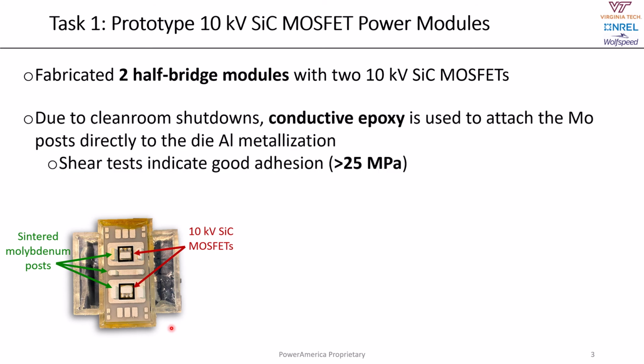And due to clean room shutdowns recently, we've switched from sintering these moly posts onto the plated silver top side of the silicon carbide MOSFETs to using a conductive epoxy adhesive, which will directly bond the molybdenum posts to the existing aluminum metallization of the die. And that enables us to get good shear tests exceeding 25 megapascal, and so that's helped us to continue fabricating modules even during the shutdowns.